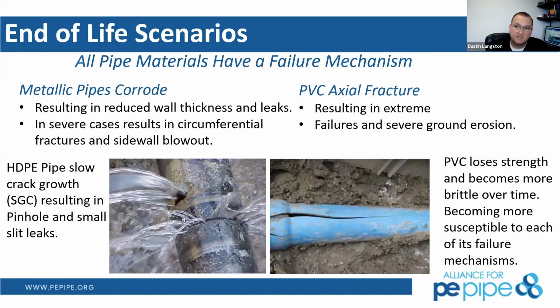And for the original 4710s over 10 years ago, it was required to have 500 hours of PENT, slow crack growth resistance. And that would equate us to 100 years in the ground service life, resisting, again, slow crack growth. And the materials we're using today, PE 4710s, are well over 10,000 hours. So, a 20 times multiplier on this 100-year service life, minimum 500-hour PENT test.